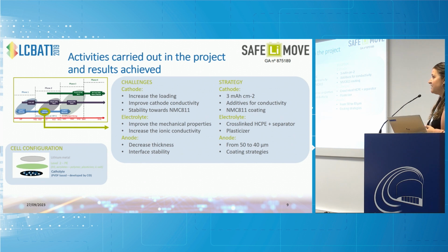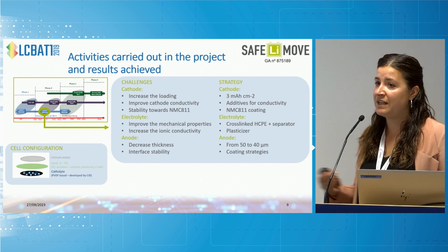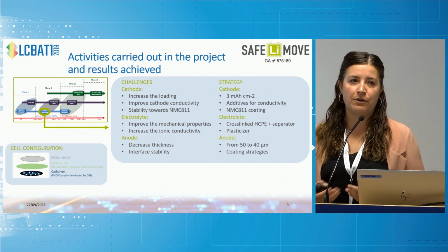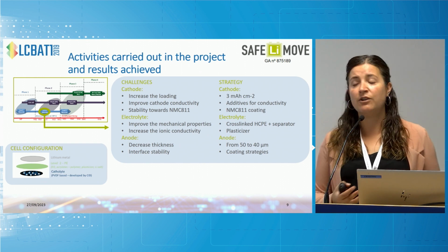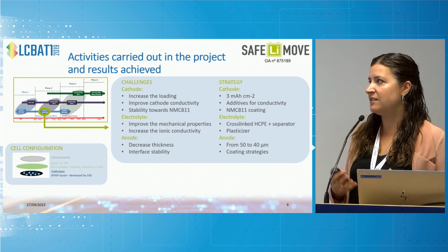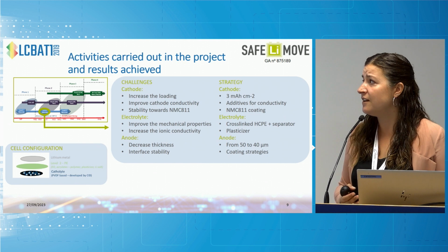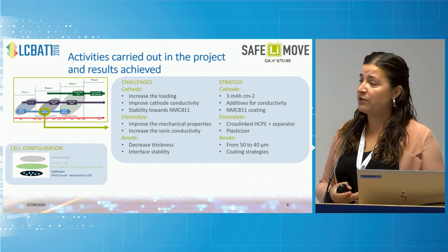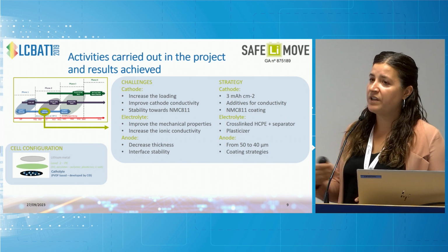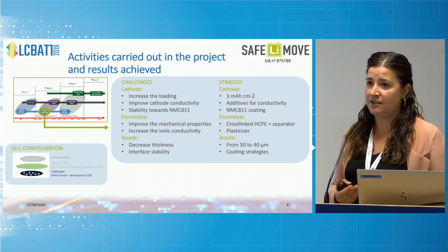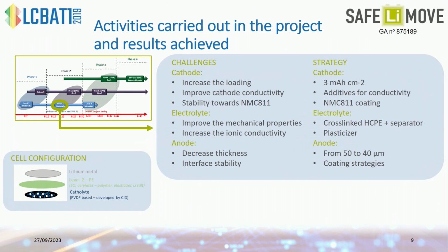So the main challenges that we found in the cathode is that we really needed to increase the loading. We are talking about a loading of 1 milliampere-hour per centimeter squared, for sure far from meeting the targets for the energy density. We needed to improve the conductivity on the cathode side. We needed to improve the stability of the NMC 811, so we know that it is very reactive during the processing as well as with the other components within the cell.